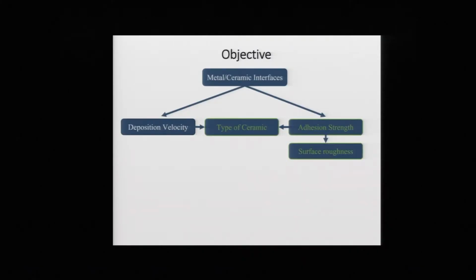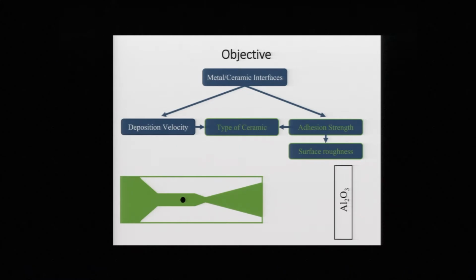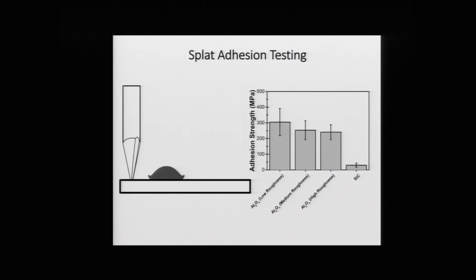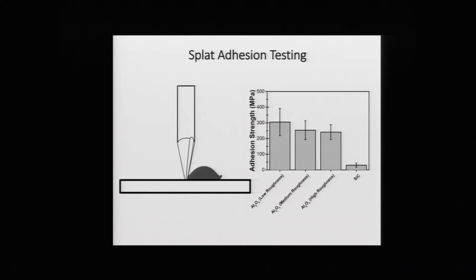So now let's look closer at the particles that bonded and how strong is the adhesion strength and how the type of ceramic will influence it and how surface roughness will influence it. To do this, we sprayed the single particles towards aluminum oxide with different surface roughnesses and then repeated the experiment with titanium deposited on silicon carbide. And at this point, you might be asking yourself, well, if you're depositing these single particles, how can you test their adhesion strength? We have a specialized equipment to do this. And this equipment effectively comes and removes the splat, or the splat is what we refer to as the particle bonded to that part. It comes and removes it and can measure that adhesion strength.